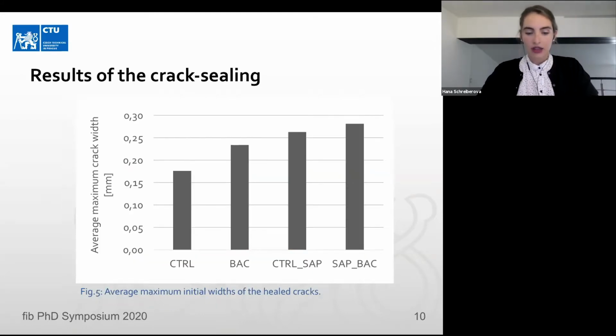In this graph, the average maximum healed crack widths are compared. In the control sample, that's without Superabsorbent, the average maximum healed crack width reached 0.18 millimeters. In the BAC samples where bacteria was incorporated, the average width increased to 0.23 millimeters. And in samples where only SAP was added, the average initial crack width reached up to 0.26 millimeters. Finally, in the SAP-BAC samples containing both the bacteria and the SAP, the precipitates could be observed in cracks with the average initial width up to 0.28 millimeters. So it reached the highest values.